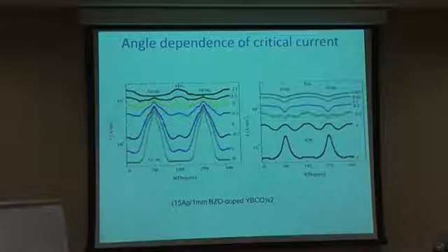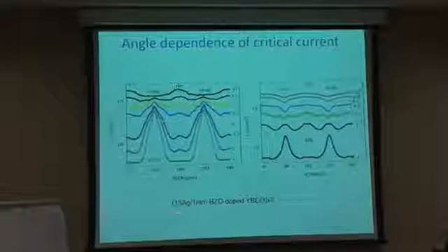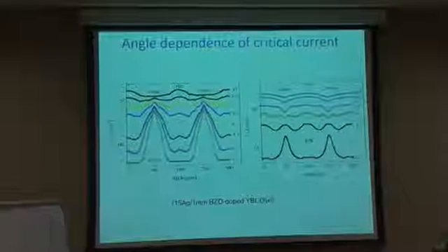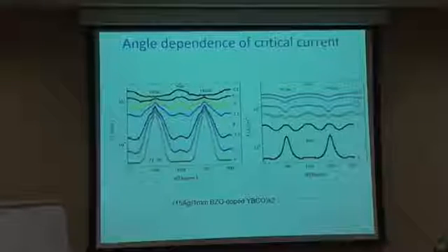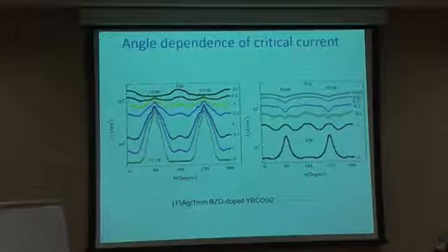Now, to imagine how little silver we use in these quasi-superlattices, for growing this is not millimeter, this is 1 micrometer, so this is a micron. To grow 1 micrometer of YBCO or doped YBCO, we need 6,000 laser shots. So obviously these 15 laser shots of silver will create just some small nano islands on a quasi layer.